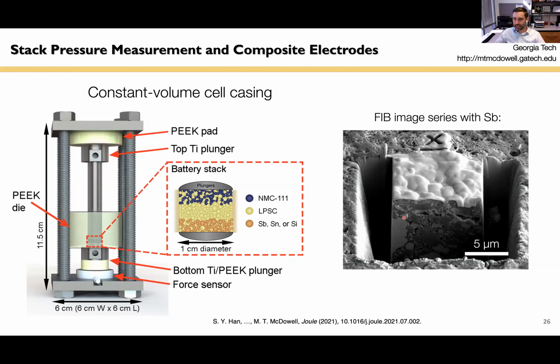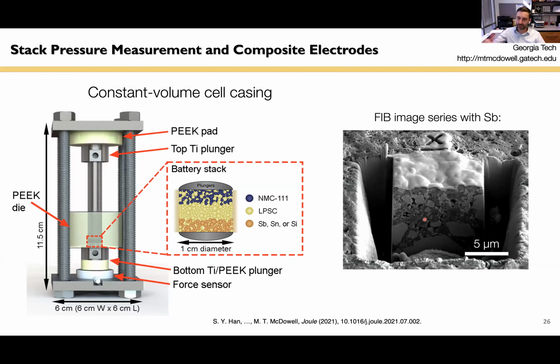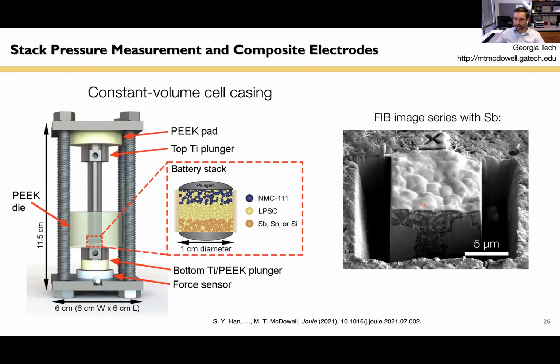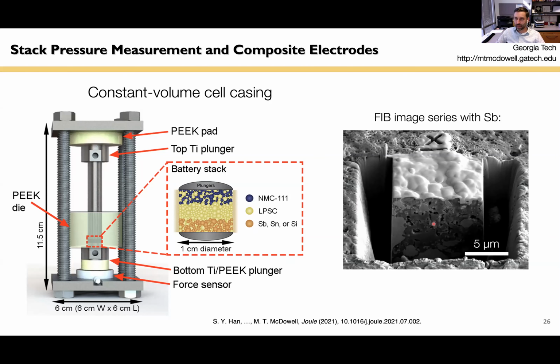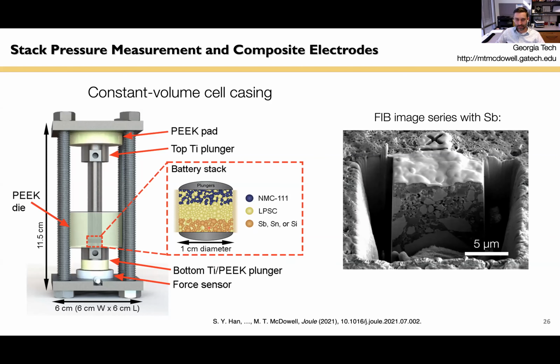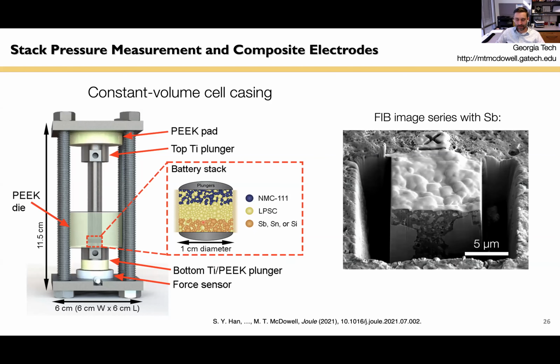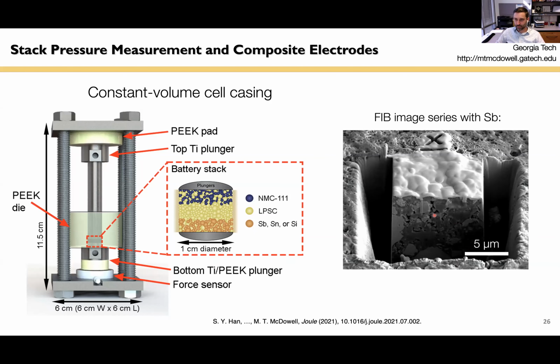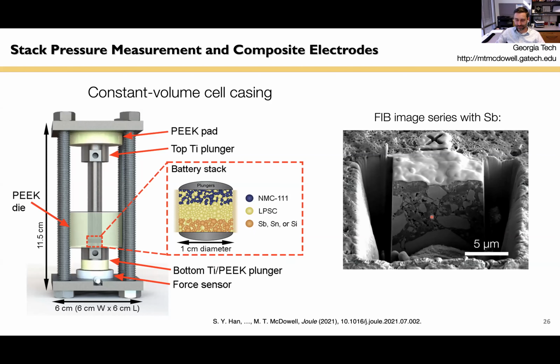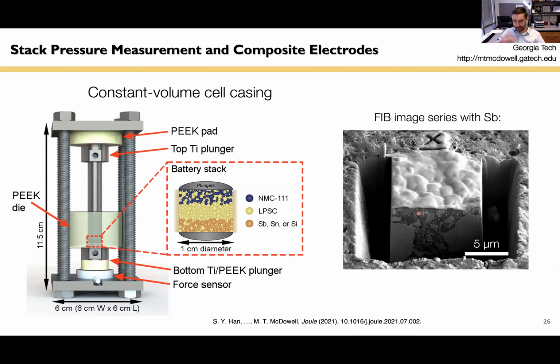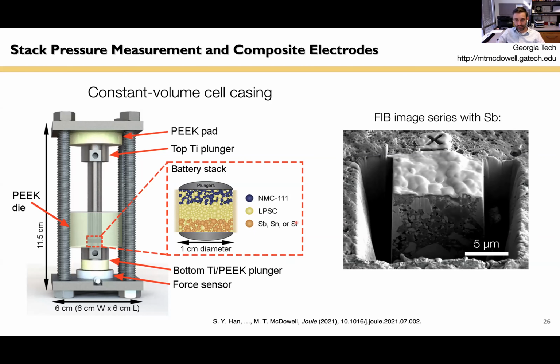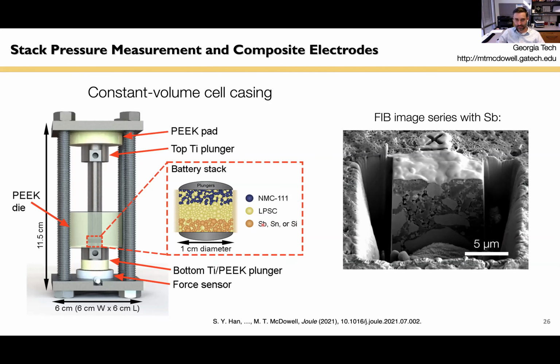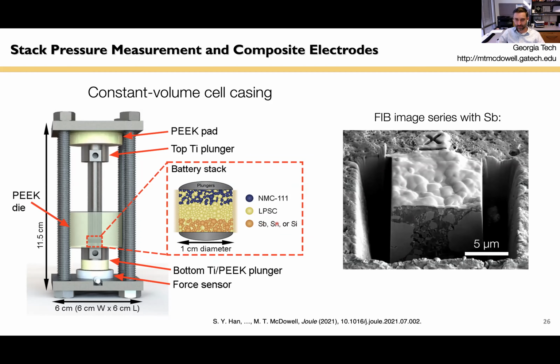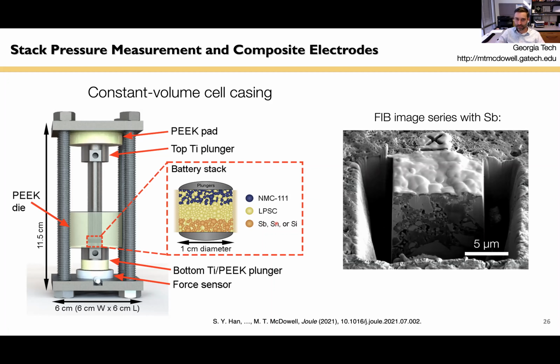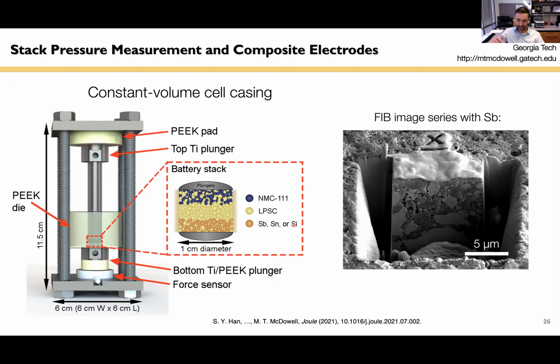This is a cool set of images over here. This is a FIB cross-sectional tomogram, basically, of one of these alloy composite electrodes. So again, this is the negative electrode in our battery down here. In this particular case, we're using antimony as our active material. I will show you data from 3 different alloys: silicon as the active material, antimony as the active material, and tin as the active material. All we found worked pretty well. Silicon, we investigated the most.